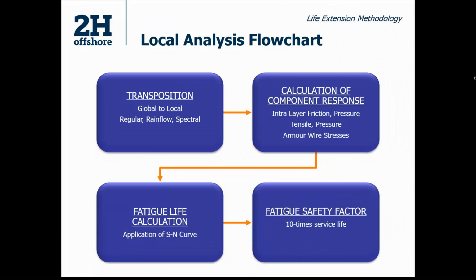After we've calculated stress and calculated fatigue, we apply the SN curve. So the curve that gives us the amount of damage that is going to occur with combinations of curvature and tension, or stress and number of cycles. Apply a fatigue safety factor, which is prescribed by the recommended practice and specifications, which is 10 times the service life, because risers are generally in high-risk areas. So they're near where humans are. They're transporting hydrocarbons, and they're generally high pressure. So the impacts to safety of humans and safety of the environment is important. So a generous safety factor is applied in order for us to calculate our remnant life.